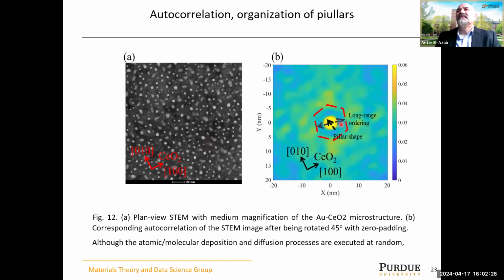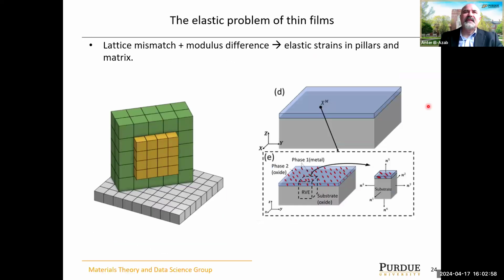So you're always within like a 2-pillar diameter region in the middle here, if your pixels are so tiny and the pixels take black and white character of the matrix versus pillar in this particular case. So we got nice agreement with the experiment, except that pillar sizes are kind of slightly off compared with the experiments. And we know why, because in these simulations, we're actually missing the elastic effects.